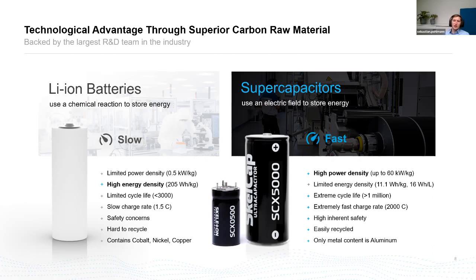Whereas in supercapacitors, you have a very easy time moving a charge away from a charged surface to the other side, to the electrolyte, to another charged surface, or just back into the electrolyte, which means normally very high power density. So very high mobility of the charge carriers means very high power density. That makes supercapacitors and lithium-ion batteries two technologies that are very different to each other, in the sense that one has very high power density, one has very high energy density. But there are other things to look at.